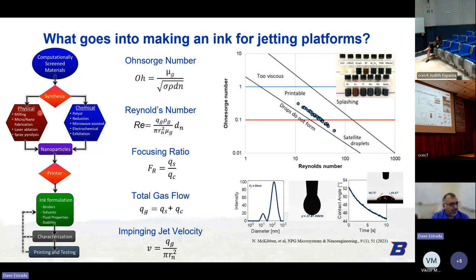We call the top-down approach the physical destruction of a bulk material, and that could be done through milling, laser ablation, spray pyrolysis, things of that nature. And so that could be like high energy ball milling, 3-roll milling, for example. And that typically gives you a powder of nanoparticles. On the chemical route, we call this the bottom-up approach, and we can use reactions like polyol, solvothermal, liquid phase exfoliation to get kind of the particles within a solution. And then we end up with the solution of nanoparticles.